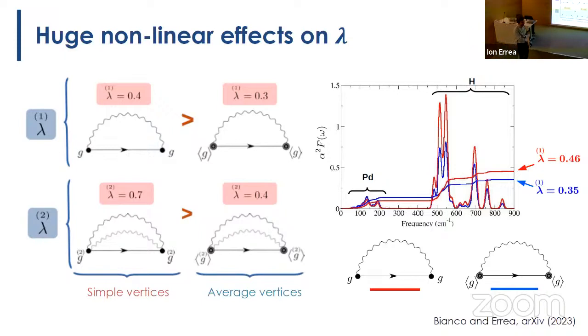So my first is related with the last question. Your assumption is that there is always a sizable electron-phonon interaction. What if a charge density wave is driven by nesting, the divergence of the electronic susceptibility? Can you calculate the onset of the charge density wave? Yeah, there is absolutely no problem. So it's not an assumption that I'm making. Actually, this is a result that we need to analyze later.